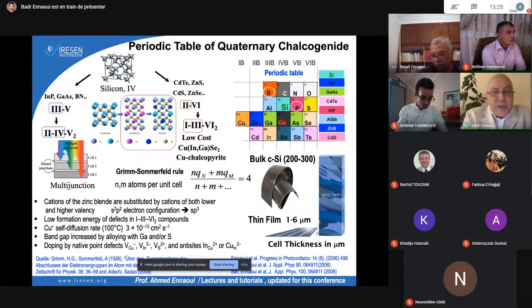But I was working very much on chalcopyrite, and these materials have a cation of the zinc blende, which can be substituted. So you can see here the two elements of the Mendeleev table can be substituted by 2-3 to get copper indium gallium selenide. And this always follows a law or a rule called the Grimm-Sommerfeld rule. So your atom will always see 4 charges, but you lose in the symmetry.